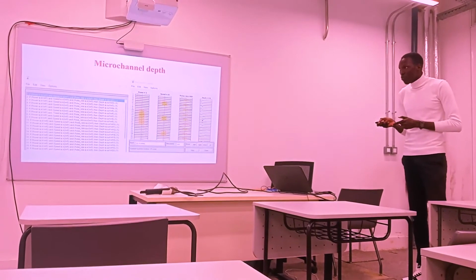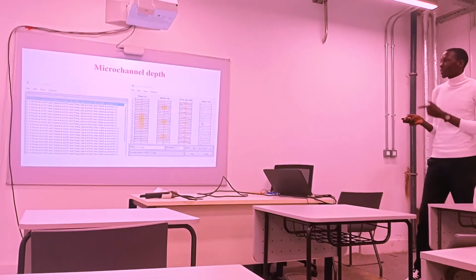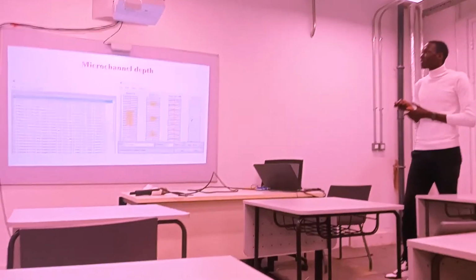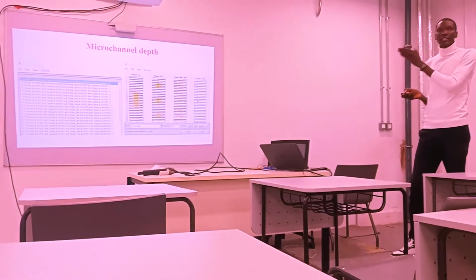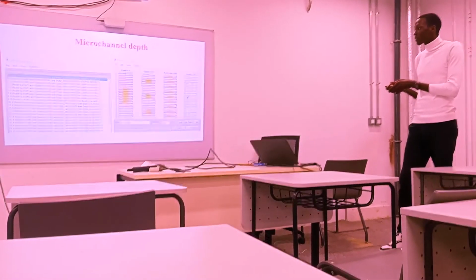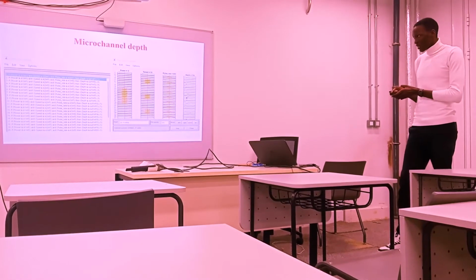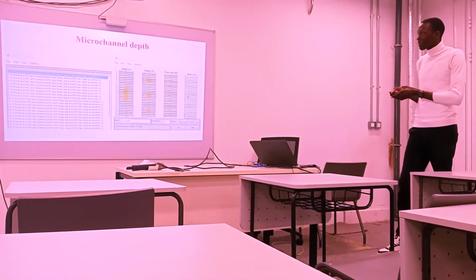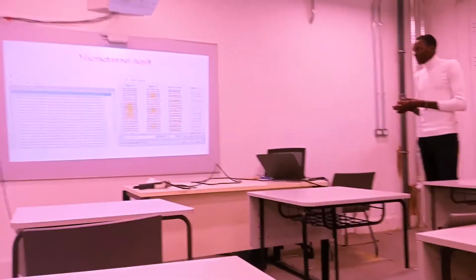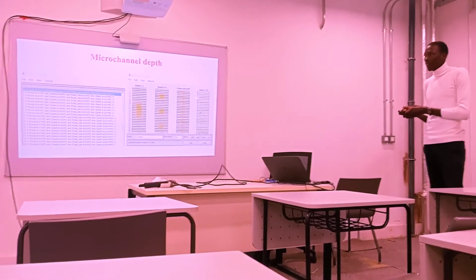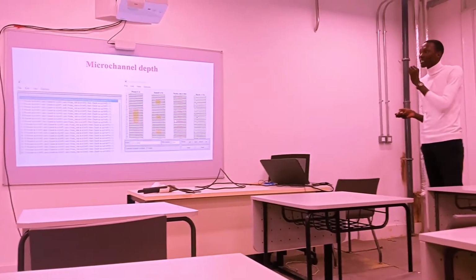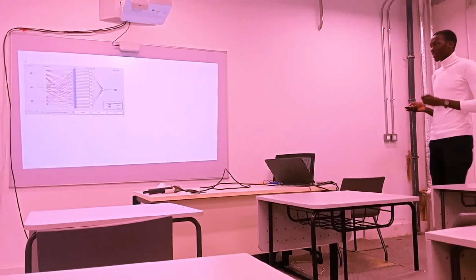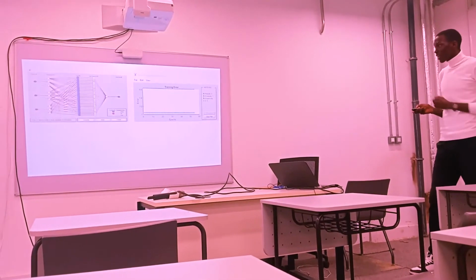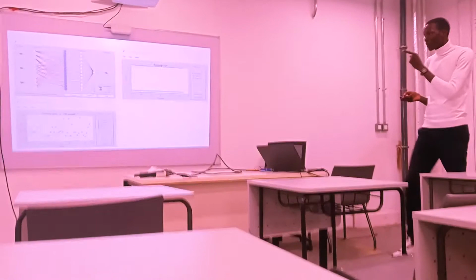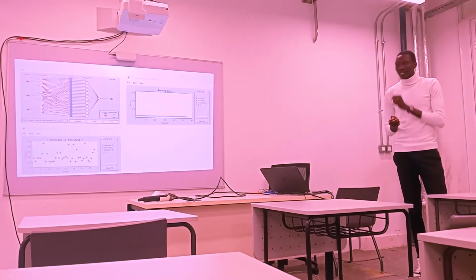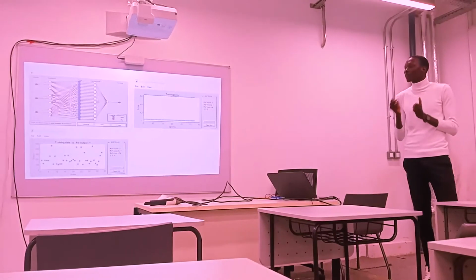These are the rules in the rule editor. These are the rules in the rule viewer. Again, you can estimate the values of the depth by entering any set of values of power, speed, and pulse rate. For example, for this one, at power of 3 watts, speed 50 millimeters per second, and pulse rate 900 pulses per inch, you get 178 micrometers, the value of the depth from the model. Then, this is the structure of the model for depth, the training error, and the comparison of the values of the training data, the experimental values and the predicted values.